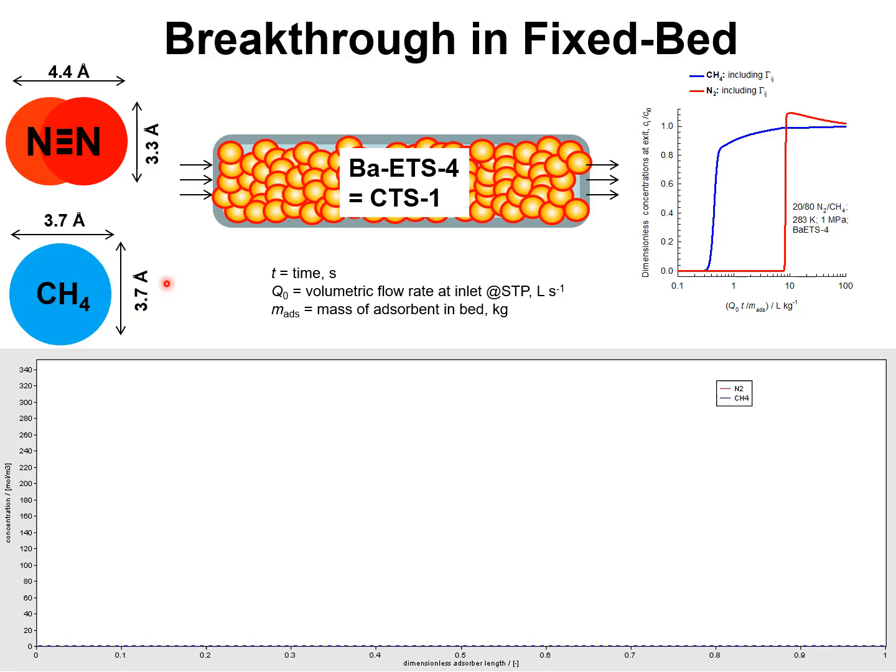After having examined the transient uptake of nitrogen-methane mixtures within a single particle of barium ETS4, let us examine transient breakthroughs in a fixed bed adsorber. We carry out simulations of the transient breakthroughs using the Maxwell-Stefan diffusion model for intra-particle diffusion, in which thermodynamic factors are duly accounted for.